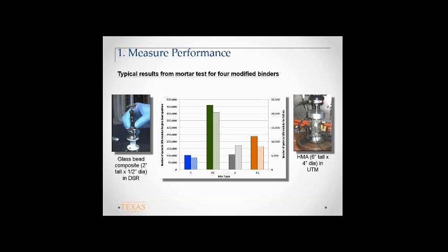I think his question is because he's having a little higher coefficient of variation on this test. This one? My next question would have been, if you had run the test, what's your variability? This one, I can tell you, is very good. It's not much, the binder test, because it's also very finely mixed and very homogeneous. But I understand that you need to normalize some of the initial differences, because small variations in the M value or small variations in the initial compliance will make a lot of difference. So you have to normalize and use the correct normalization. I can share with you a dissertation using this that addresses the variability question.